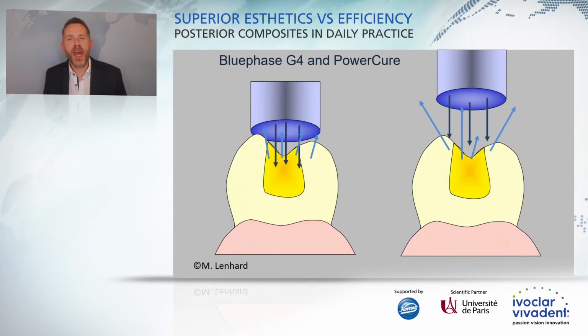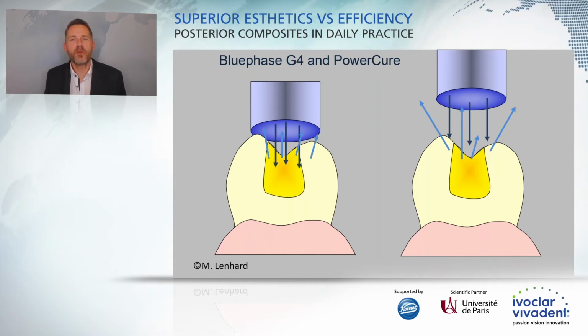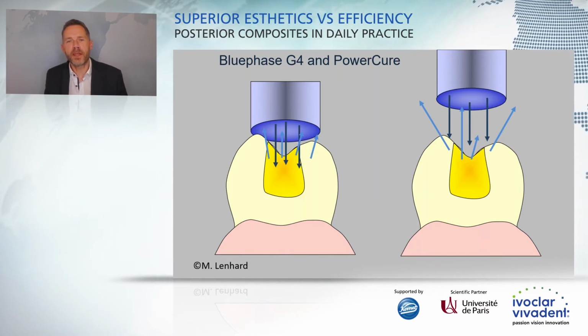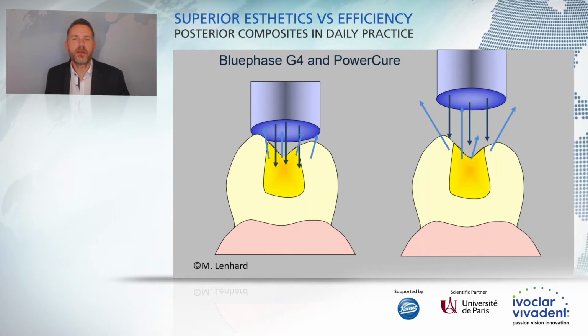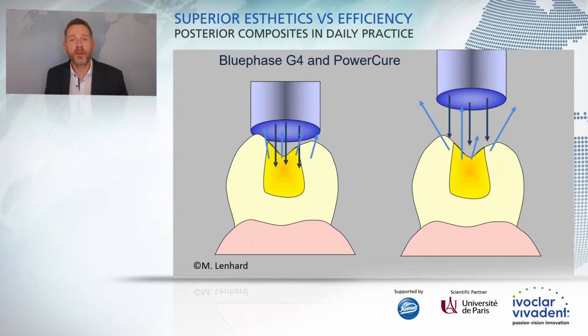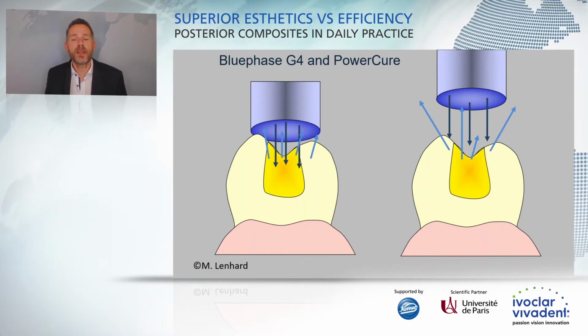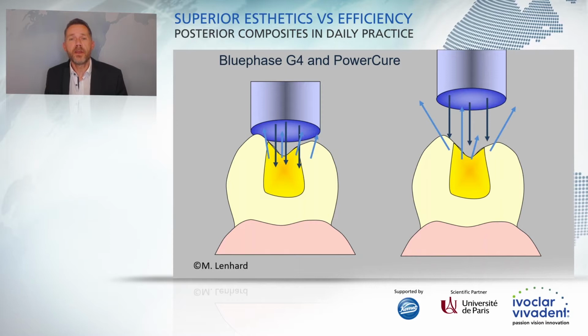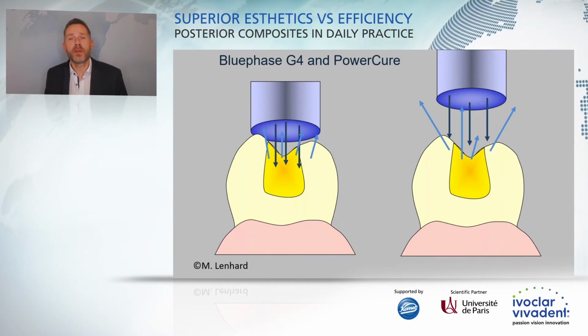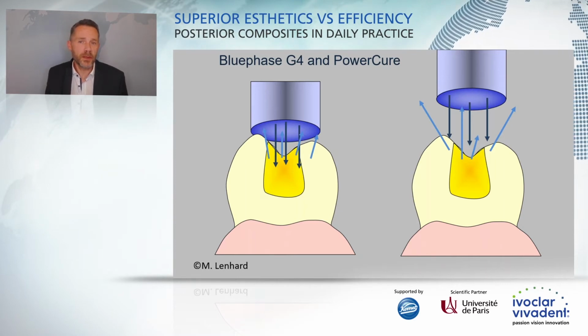As I said, they have a built-in educational tool. These curing lights measure the amount of reflected light that is reflected from the tooth surface, and these lights will realize if the amount of reflected light from the tooth surface is too low. The light will actually realize that you are not close enough to the tooth surface, you're not polymerizing adequately, and the light is giving you a warning that you have to concentrate. Actually, it turns off if you do a major mistake there. So that is very helpful, especially if you do not do the light curing yourself, but you let your dental assistants or the dental nurse do that.